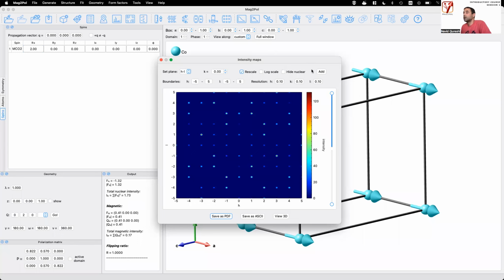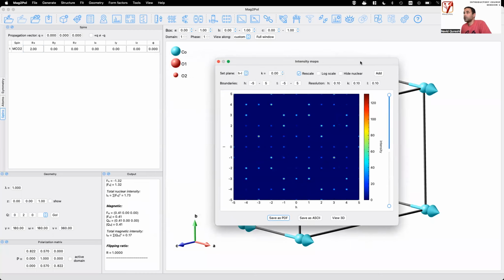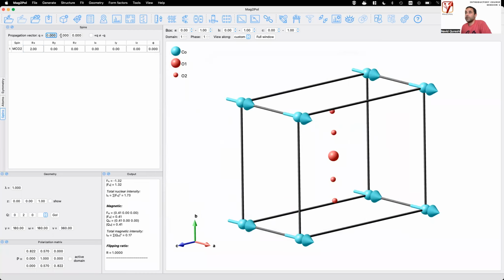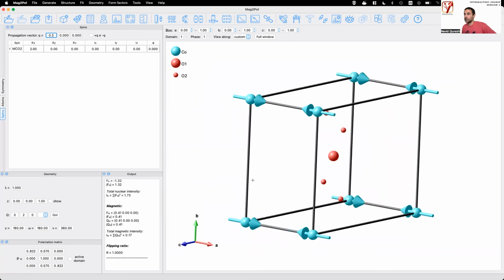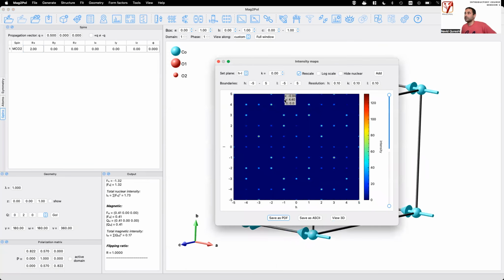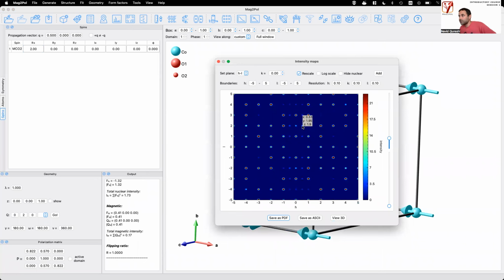Then there is another feature, which I don't know if it's very useful, but you can change your magnetic structure in the main window. So here I will just change the propagation vector, which will create an antiferromagnetic structure. And if I come back to my intensity map and I click on Add, then you will see how we have some half integer reflections here, which were not there before. So you can add different propagation vector components to the same map if it's something you want to do, or if you have a magnetic structure with multiple Q components. This can also be done using magnetic domains, but we will see that on another day.